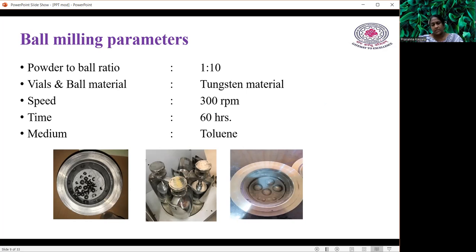So here, basically, is how the preparation of the hybrid composites takes place. Before processing, all the powders are preheated so that all the moisture can be removed. Then the required compositions of aluminium 7075, silicon carbide and graphite are blended in a high energy ball mill using tungsten balls of 10 to 50 mm. The ball to weight ratio is 1:10, and the milling period is about 60 hours. Finally, the blending and grinding procedures were done at 300 RPM, using the toluene medium to prevent oxidation or sticking of powder on the vial wall.